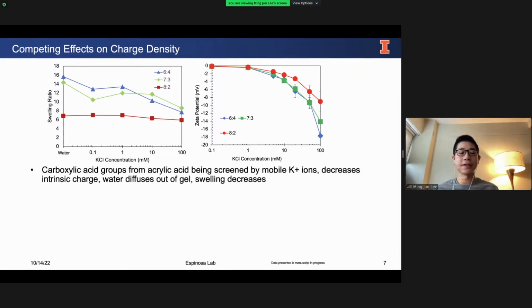So what are we seeing here? What's happening? I believe that the carboxylic acid groups in the acrylic acid component are being partially screened by the mobile potassium ions in the salt solution, which decreases the apparent overall intrinsic charge of the hydrogel. So with this difference in the osmotic pressure, water would diffuse out of the hydrogel, leading to a smaller volume, and so the swelling of my hydrogels decreases.